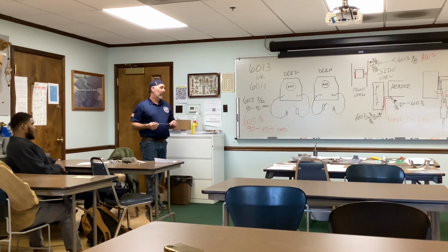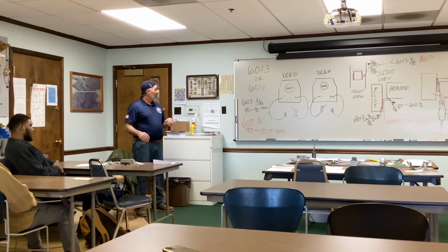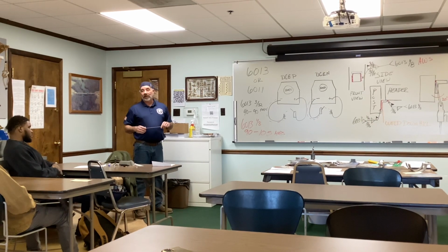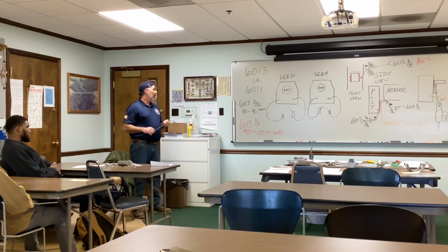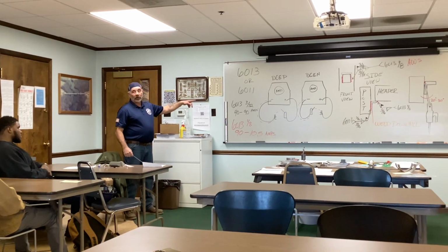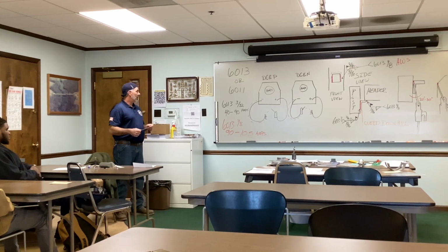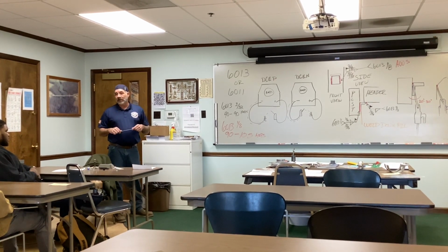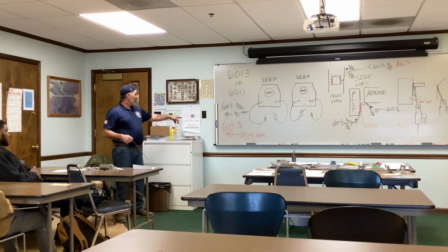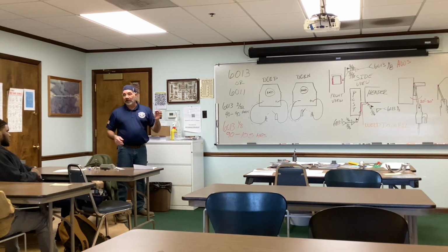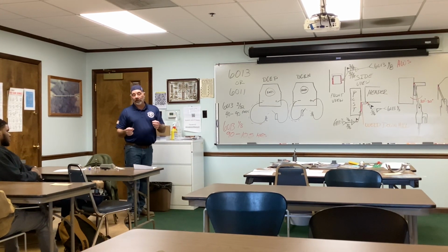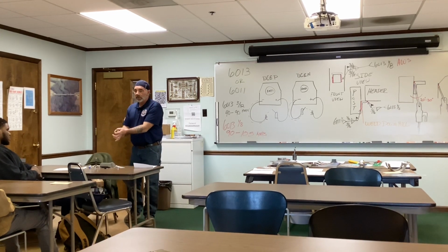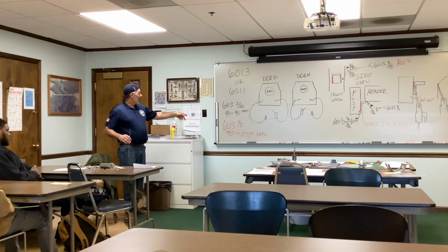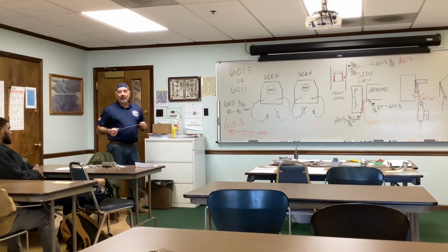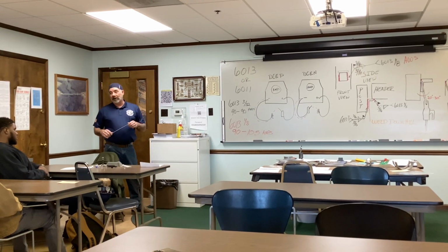And then the other thing, knowing what rod selection to do, is your amperage, how to set the heat on the machine. So generally with a 60-13 3/32 rod, you're going to set your amperage around anywhere from 40 to 90 amps. And then the 60-13 1/8 inch, which is what I have in my hand, this is 1/8 inch thick, and that all has to do with the thickness of your electrode, not just your flux, but just the electrode. So with the 60-13 1/8 inch, you're going to generally set your amps from 90 to about 105.